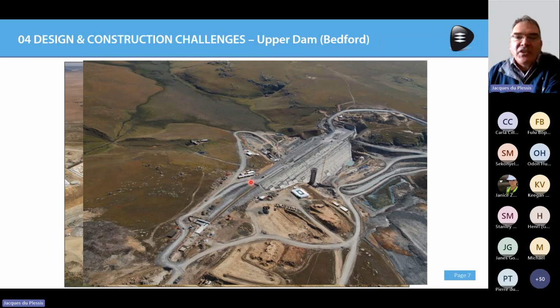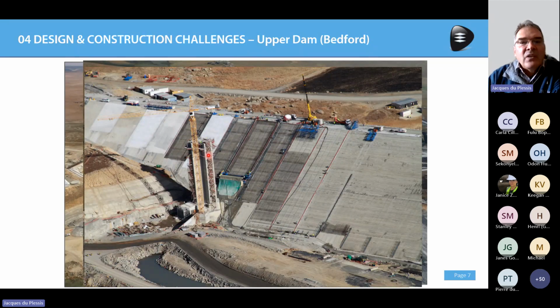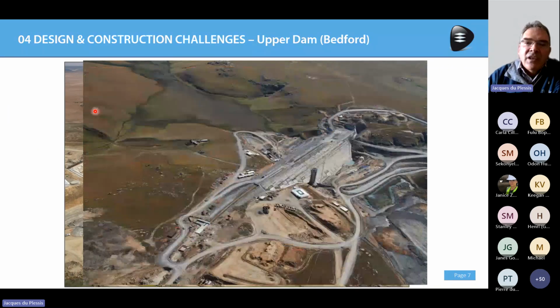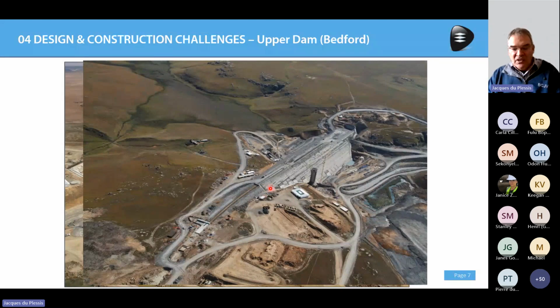Okay, thanks, Alan, for the question. You see this concrete face, if we can just look at the next. So the concrete face panel, you can see it becomes shorter. And at one point, it can't pinch into nothingness. So for that reason, we stopped the concrete face rockfill dam at this point. So you need a separation between your concrete face, and you also need something to place your clay core cutoff against on this side. So we have a sloped, I think it was an 8-in-1 slope, concrete slope there, and then downstream of this clay core, we had a chimney filter and a blanket drain as well. Yes, I hope that answers the question.